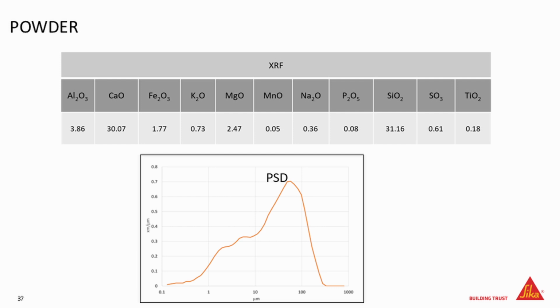Now let's have a look at the powder. Again, you see the particle size distribution, and the majority is below 100 microns. What is also interesting is the chemical composition, because we have a lot of calcium oxide in that powder. That's clear, that's the cement stone. The silicon oxide comes from the aggregates, so you still have some dust of the aggregates from the friction. But the calcium oxide is quite significant, and this could also be a potential source for cement production, because basically what you need for producing clinker is a calcium source.